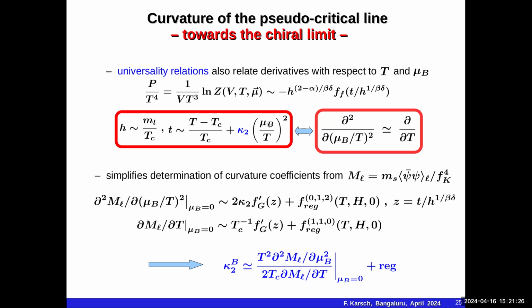And as we eventually at the phase transition point need that the scaling field T has to vanish, we can use derivatives of the order parameter with respect to chemical potentials and temperatures respectively, and find the condition that is needed to make the reduced temperature variable vanish. So that allows us to define the curvature coefficient in terms of a somewhat simpler quantity, namely just second order derivatives of the order parameter with respect to baryon chemical potential and with respect to temperature.